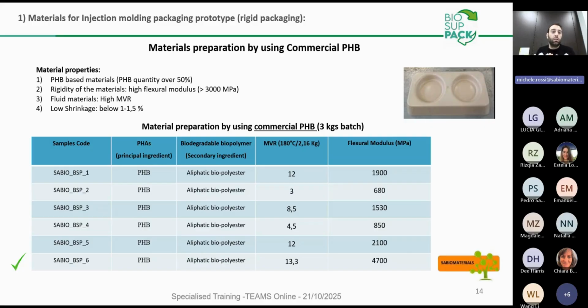Here you can see an example of 6 compounds that we have obtained. We obtained more or less 30 compounds, but here, to make it easier, we show only the best compounds. But from these 6, only 1 represents for us a very good material because it presents all the characteristics, the first requests for the technology, meaning a higher melt volume rate, and 180 degrees with 2.16 kilos is 13, the maximum that we have obtained. And also the flexural modulus is the highest that we have obtained, 4700. The main ingredient for all these compounds is PHB. The rest of the ingredients are aliphatic biopolyesters that permit formulating a potential compound useful for this application.